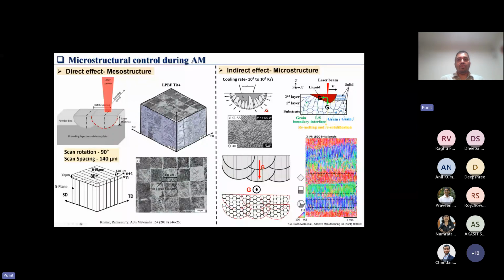What is happening here is that when you rotate your G, you can rotate the direction in which the cells grow. Here you can see that when your cell is growing in this direction, you have a 0, 1, 1 texture. If your cell is growing perpendicular to the plane, you are essentially growing a crystal in the 1, 0, 0 direction. By doing this, you can have very good control over the texture of the material. This is what I wanted to highlight as the indirect effect on the microstructure of the material. This kind of control you have in additive manufacturing usually doesn't exist in conventional manufacturing processes.